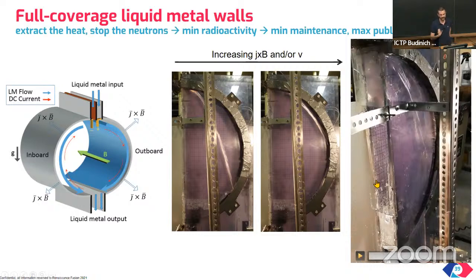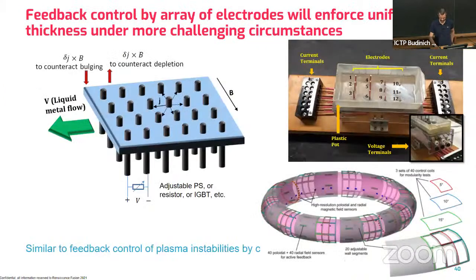This is a 1 centimeter thick flow of gallium indium tin, a convenient material for experiments at room temperature because it is liquid at that temperature. It is not what we want to use in the plasma. In the plasma, instead, in contact with the plasma, we use lithium. Before I describe our lithium solution, a quick word on stability.